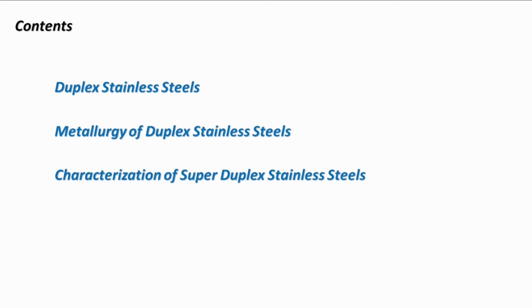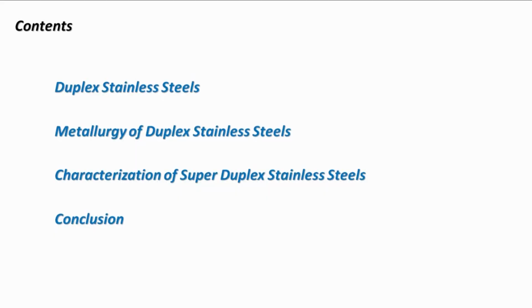foundry's practical situation. And the reason for ASTM A995 super duplex stainless steel is that the entire industry is now turning from super austenitic stainless to super duplex stainless steels because of their enhanced corrosion resistance along with the mechanical properties. So today we will see duplex stainless steels, the metallurgy of duplex stainless steel, and the characterization of duplex stainless steel using various methods like metallography, XRD analysis, SEM and EDS analysis, and interpreting various phases that are forming, and we will see some conclusions out of that.